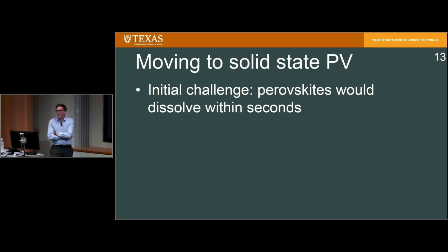And so there was another challenge that was, I think, related to the relatively low efficiencies at the beginning of these perovskite solar cells, is that perovskites would dissolve in seconds. These things were still using a liquid electrolyte. And so how they made these perovskite solar cells in the beginning is they first reacted the perovskite on the TiO2, they'd expose it to the liquid redox couple, and they would run as fast as they could to the solar tester to test these things before they dissolved within 60 seconds.